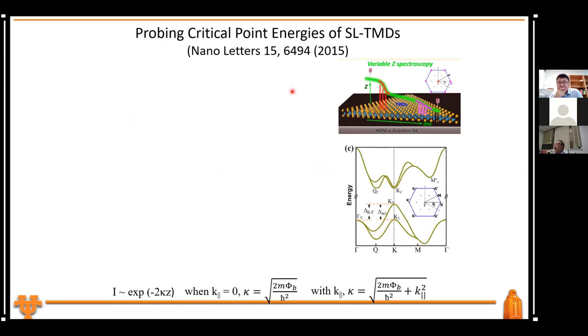Say if you have WSe2, okay, then you think about this generic band structure. If your tip bias is right here, right? Your tip Fermi level is right there, then you are extracting electrons from the valence band. Then because the gamma point has a low K parallel, your tunneling probability is really dominated by the states near the gamma point. Only when you pass that, when the states at gamma are no longer available, then you start picking up the states near the K point.